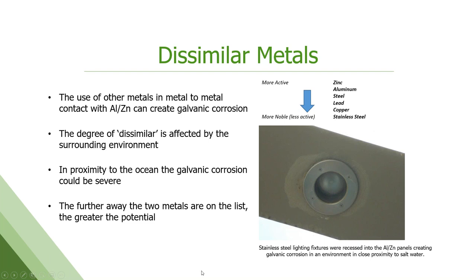If you're in a corrosive environment, and it can be corrosive air, corrosive moisture touching it, the further away two metals are on this list that are in contact with a corrosive atmosphere around it, the more active metal is going to sacrifice itself for the more noble metal. So what we have here is a stainless steel lighting fixture recessed through painted galvalume with no barrier between them. So they're in direct contact. This home was about 300 feet off the surf break outside of San Diego. So highly corrosive environment.